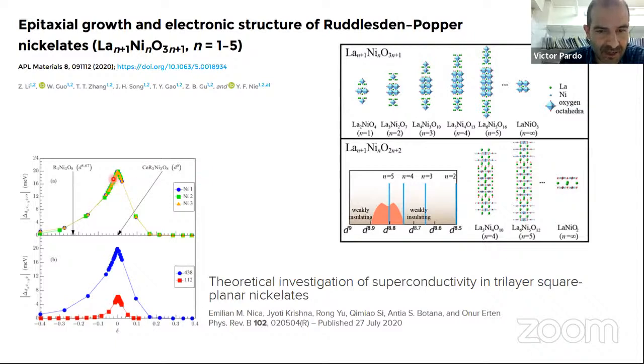What the calculations say, what Antía Botana, Onur Erten, and their collaborators have seen, is that if you consider a t-J model just for the x squared minus y squared band, the superconducting coupling strength would be much larger in this 438 than it is in the 112. So it is worth trying to pursue these compounds, trying to find these samples and see if superconductivity exists in them or not. We will learn a lot just by knowing, even if superconductivity does not appear in them.